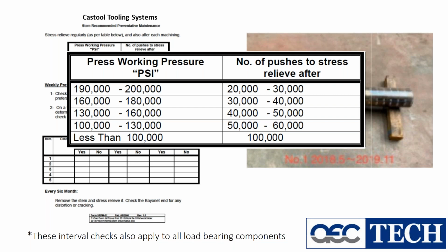Reason being, the increased pressure that's required to push that billet through that longer container has to be done at the push end of the press, which is not translated to the face of the die. So be aware of what that is. Try to keep this as part of your PM schedule and stress relieving the stems.